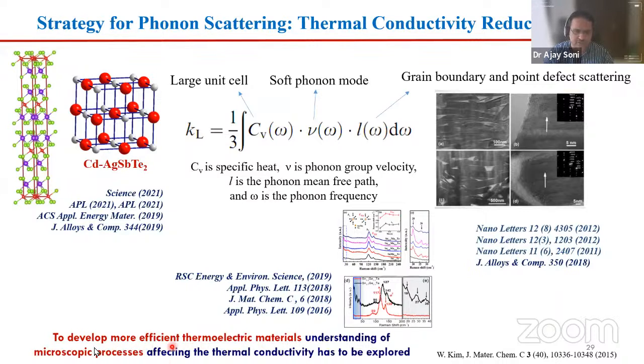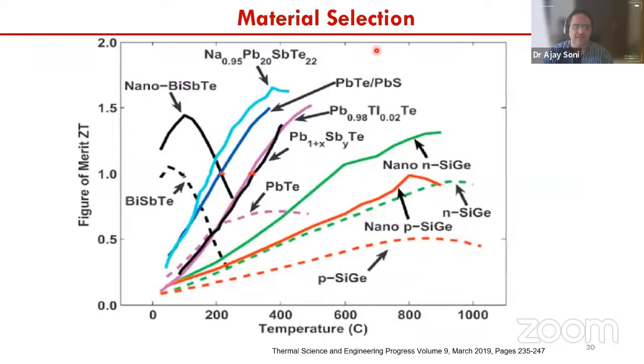So if you want to create efficient thermoelectric materials, you need to understand the microscopic processes which are controlling the thermal conductivity, and if you can tap in, then perhaps you have the advantage over there. So I will just take a few examples in the materials aspect. You can see this is the temperature range of the thermoelectric materials, and this is the figure of merit. The bismuth antimony telluride or bismuth telluride based materials work in the low temperature, like room temperature applications. There are materials like lead telluride based materials, which work in the mid temperature range, and there is silicon germanium, which works in the high temperature range. And you can see the thermoelectric figure of merit is around 1.5 or something. Recently we have achieved a figure of merit of 2.4, which goes beyond this particular figure.